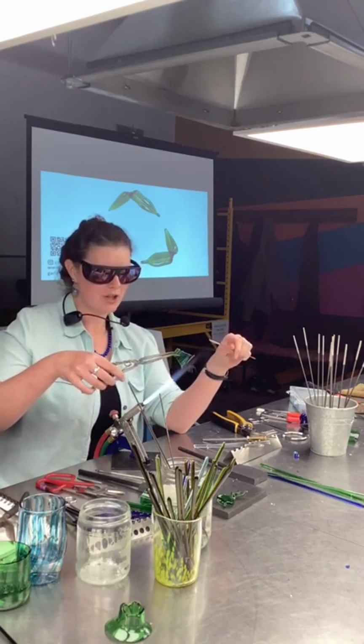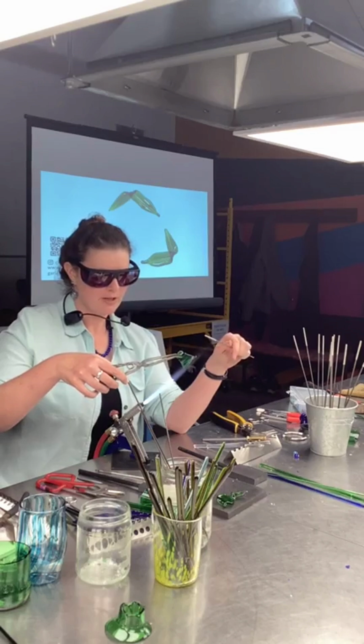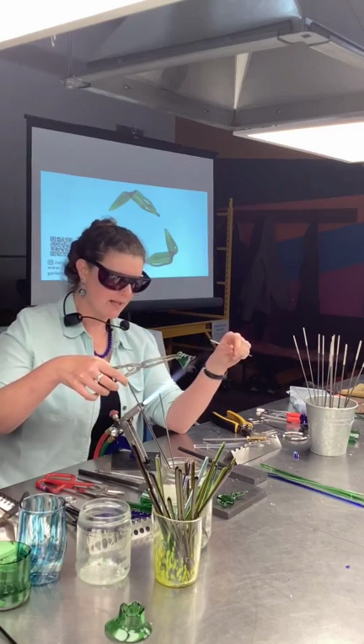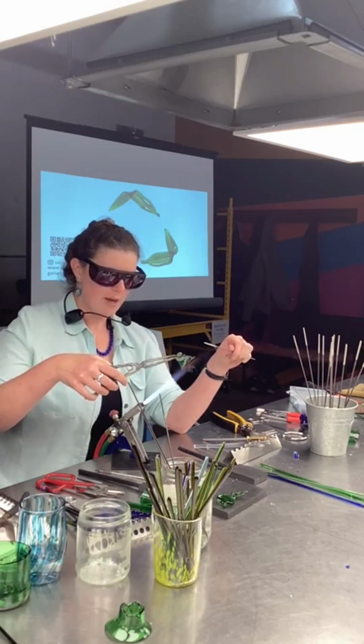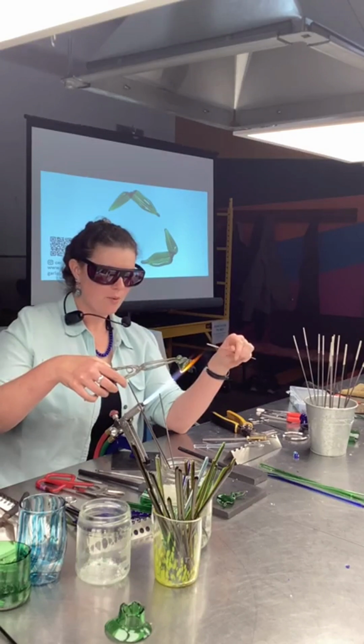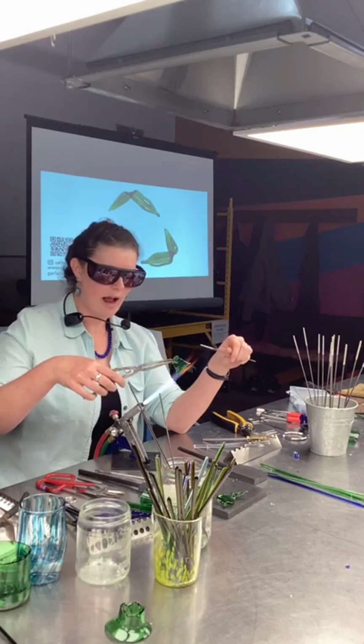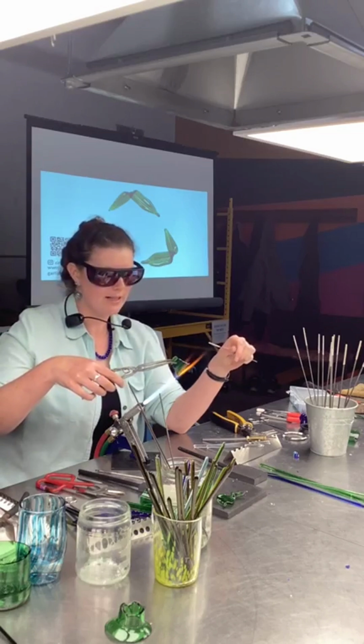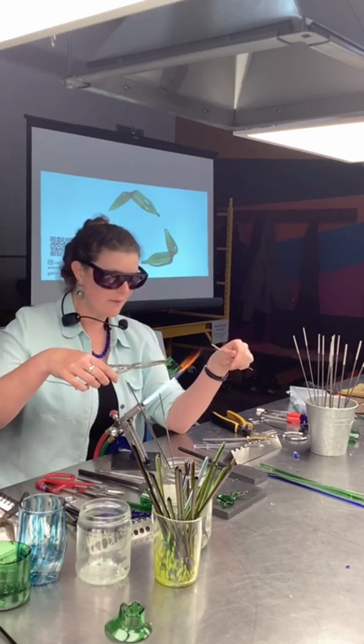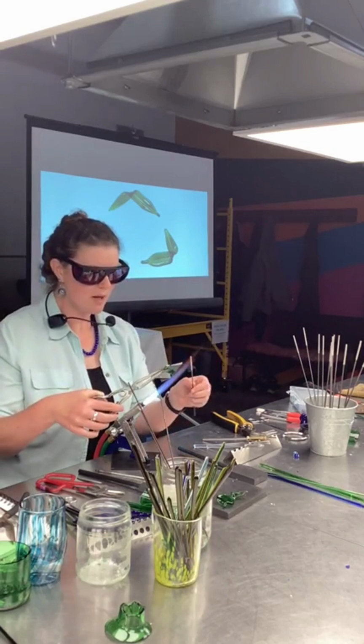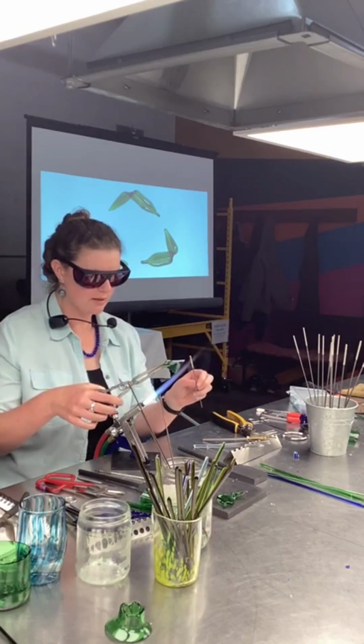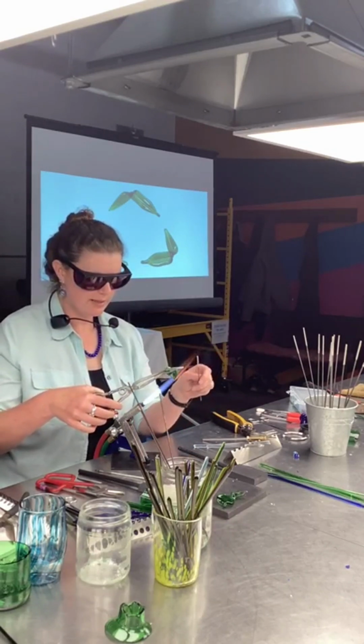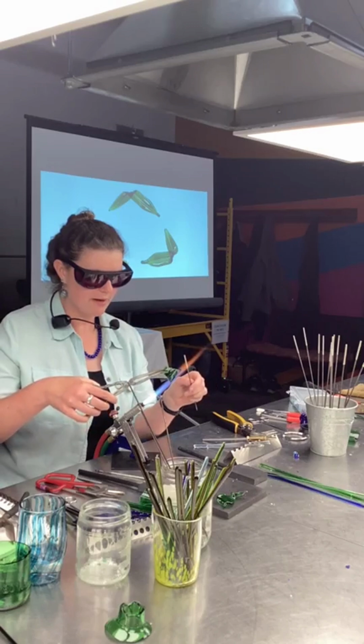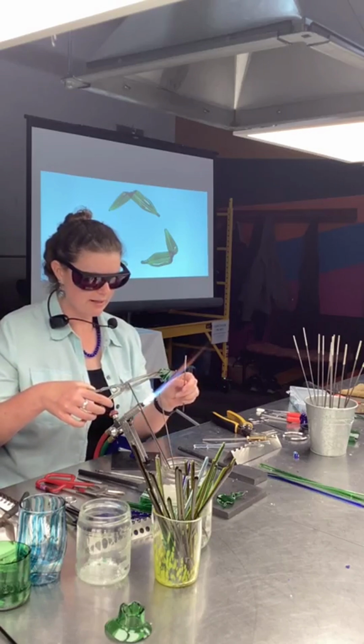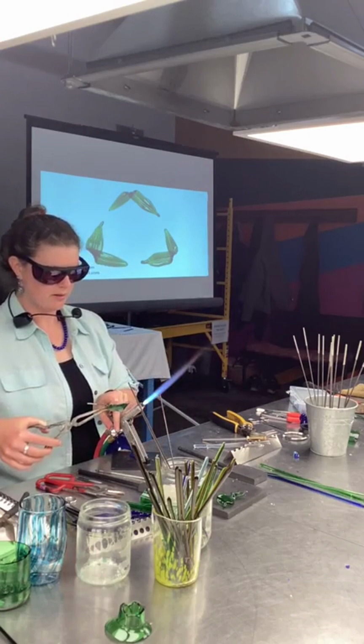And you're just going to wind this shard up as best you can. So it might have some air pockets in it, that's fine. But you've got to be really intentional, really gentle. It'll have cracks you can't anticipate where it has stress in the glass from where it's smashed. That's fine. But you want to make sure the whole edge is hot. The whole bead release is hot. So you can see that glow in the blue right there. Start to see the glow in the bead release.